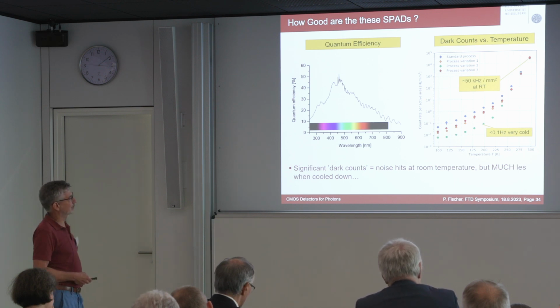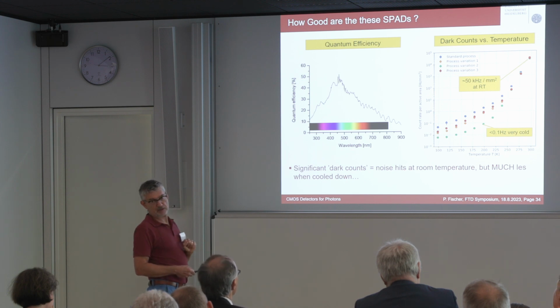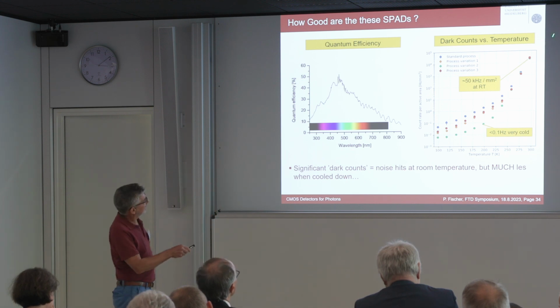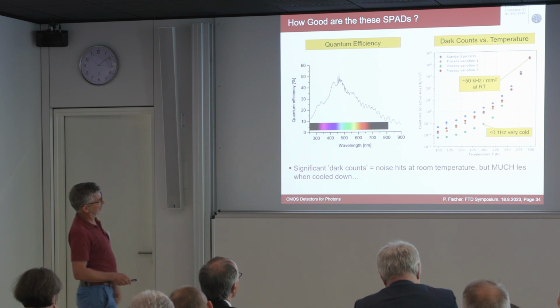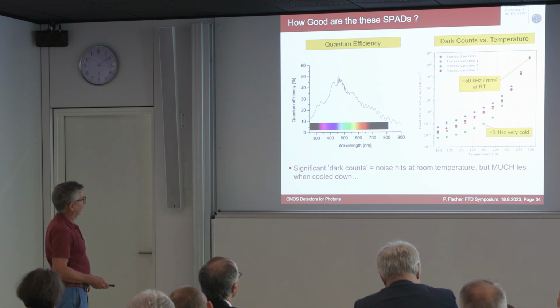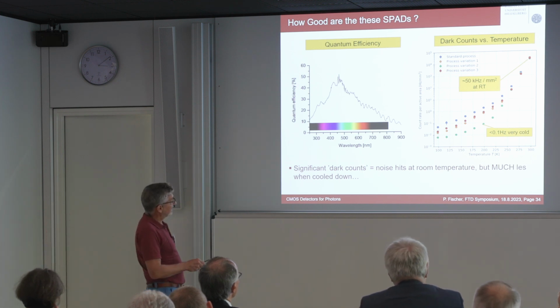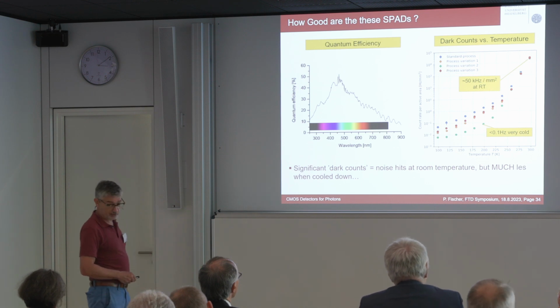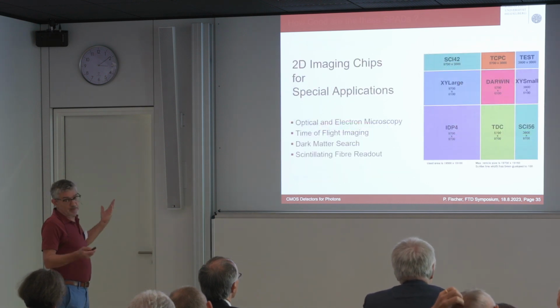This is what all the vendors are now doing for these low temperature experiments, because the dark counts don't go down as much as you would like to. You have to fight this tunneling effect. So these are really excellent devices at cold temperatures. At room temperature, it depends on the application.